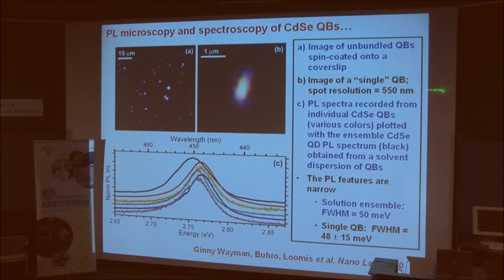But remember, the resolution of this optical experiment is rather low, and so that belt looks like it's roughly 550 nanometers wide, but it's only 7 to 15 nanometers wide, and it's about roughly a micrometer or so long. And we can measure the photoluminescence spectra from a bunch of individual belts, and they all line up very closely to the same energy value, telling us that the thicknesses of the belts are remarkably uniform. Remarkably uniform, more uniform than the diameters of the wires that we can make.